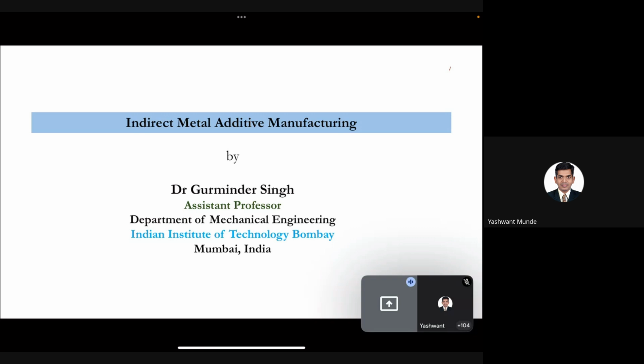Other examples are some ceramics which have a very high melting point, more than 3000 degrees Celsius and even more than 4000 degrees Celsius. They can easily be fabricated by this method. Also, some crack-prone materials, which develop huge stress during solidification and get cracks, like some nickel-based alloys, even Inconel 718, are very difficult to make by laser, but can be easily fabricated by this method.